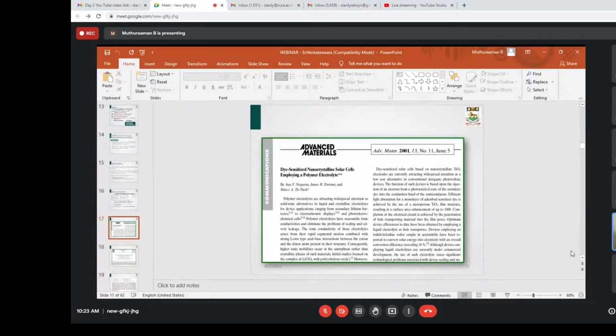So in 2001, as I told you, A.F. Nogueira and Marco De Paoli were the first to introduce the polymer in the pre-existing electrolyte. This is the first time they introduced the polymer. They got around 4.4 to 5% efficiency, but the stability improved much, while the efficiency went down.